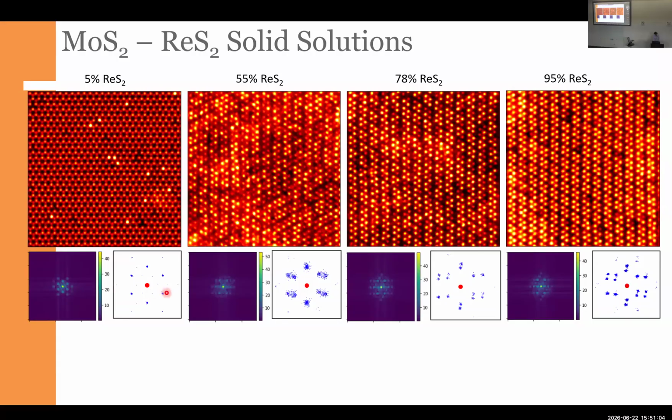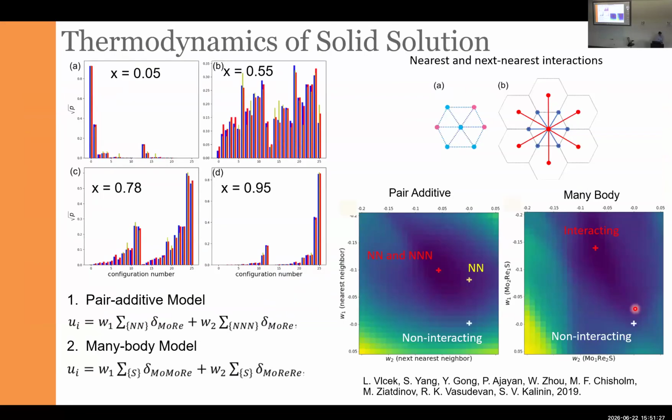And of course, it's very easy to analyze because, for example, if I calculate the pair distribution function, you can see that here the neighborhood is almost ideal, low noise and no distortion. Here you can see that the peaks start to broaden and split, and here the peaks have split, but they become narrow. So the disorder is lower, but there is a symmetry lowering transition. It turns out that for systems like this, we can do the direct mapping between this Ising model and the images that we observe in electron microscopy.